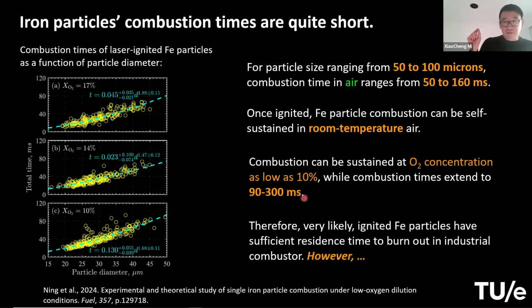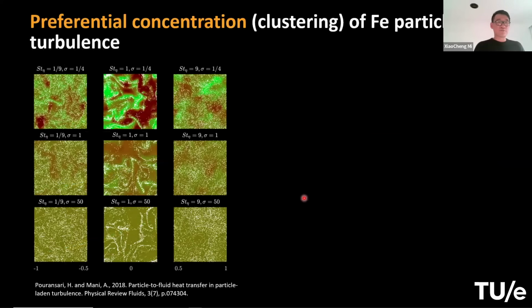So very likely in realistic burners, because they are meters long, the particle should have enough residence time to burn out, because the combustion time after ignition is quite short. But there is one phenomenon that we need to be careful with. In all these larger burners, particles are burning in turbulence, right? There is a phenomenon called preferential concentration, or clustering, which can happen to solid particles or liquid droplets in turbulence. And this normally happens when the Stokes number is around 1.